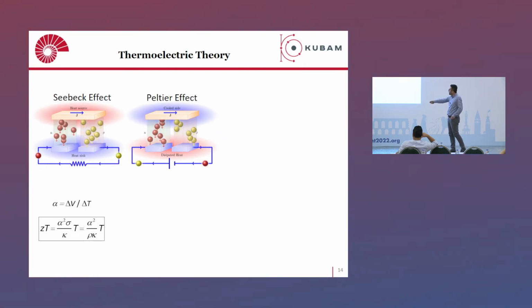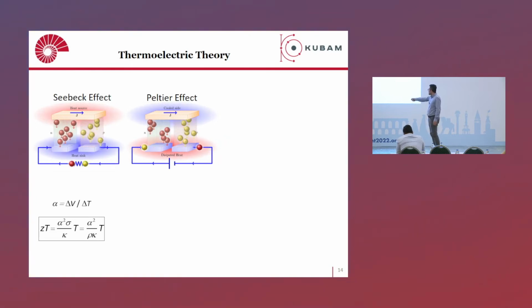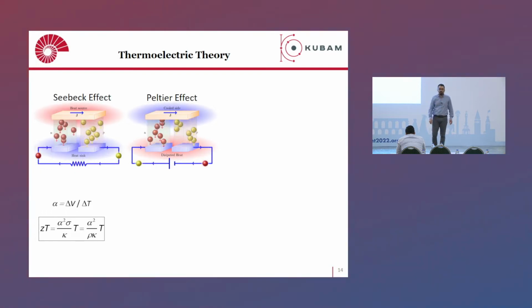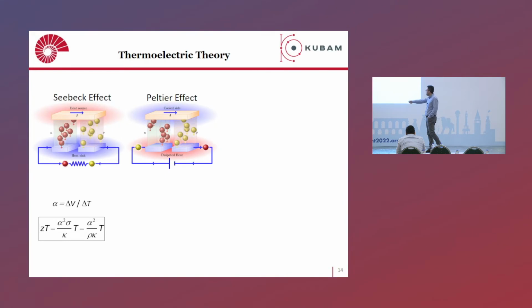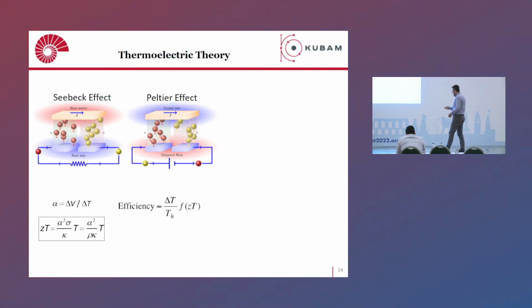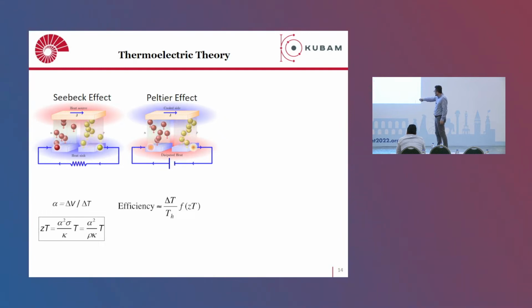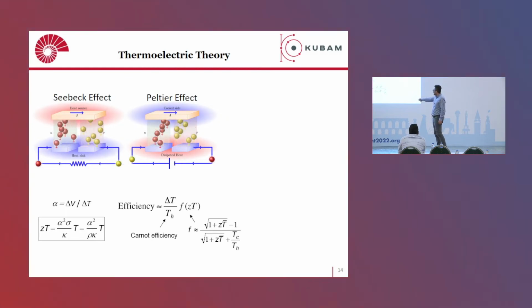So in the materials part, we have this ZT, the dimensionless thermoelectric figure of merit, related to the Seebeck coefficient squared times the electrical conductivity divided by the thermal conductivity times the temperature. For high thermoelectric efficiency, we try to get good electronic properties but at the same time lower the thermal conductivity, which is quite demanding and hard. The device efficiency is related to the Carnot efficiency times a function of this material ZT. And you can see that rather than having a high ZT at one particular temperature, we target a high ZT over a large temperature window so that we have a high average ZT, basically.